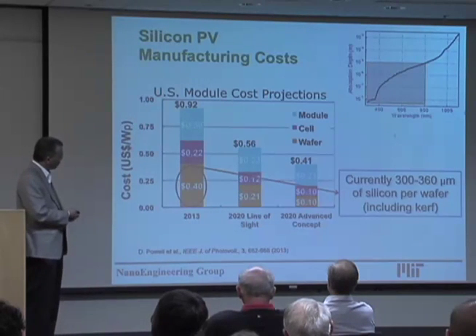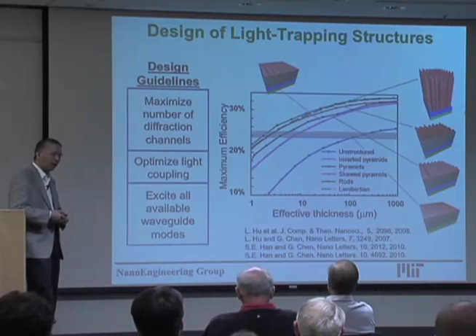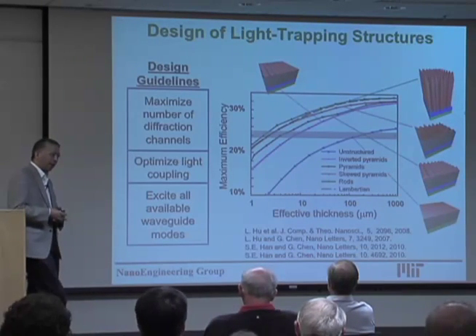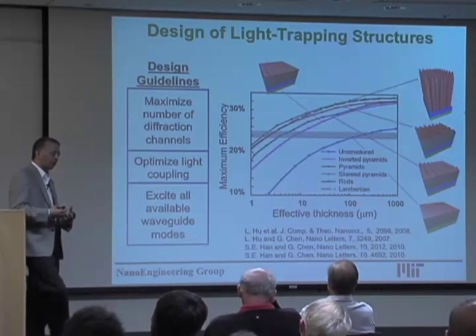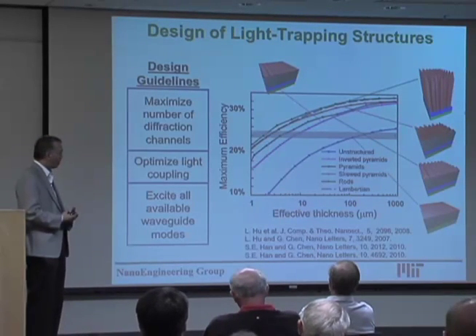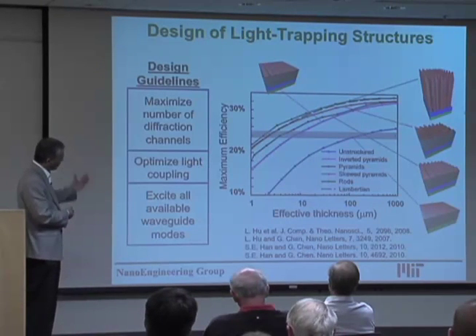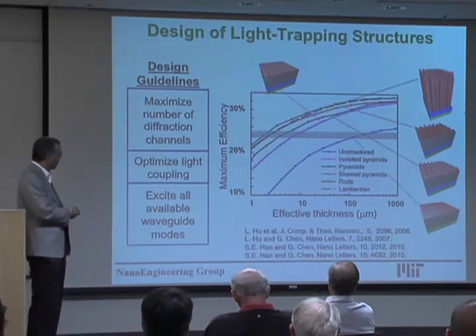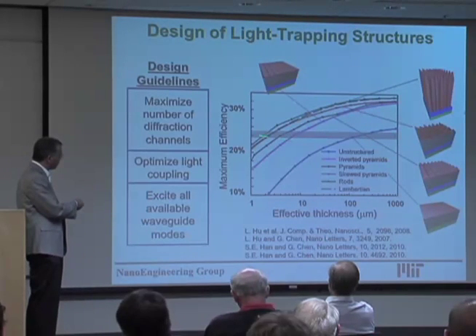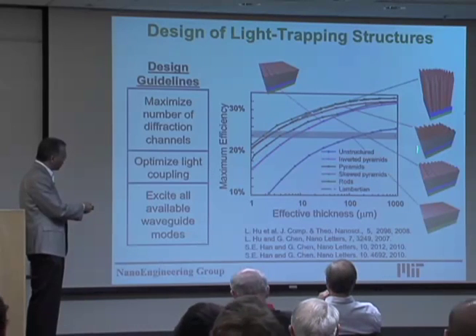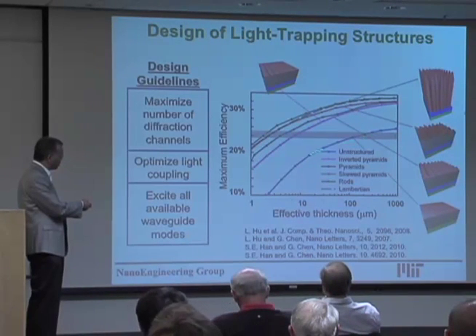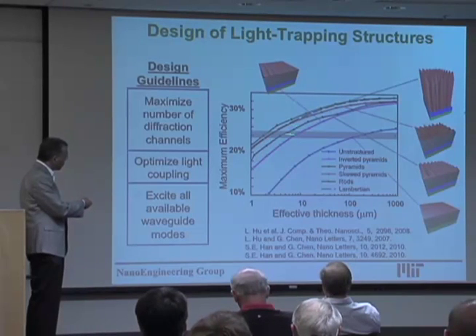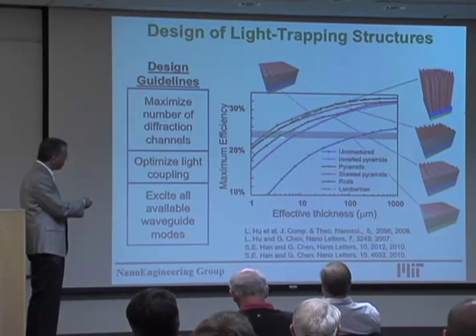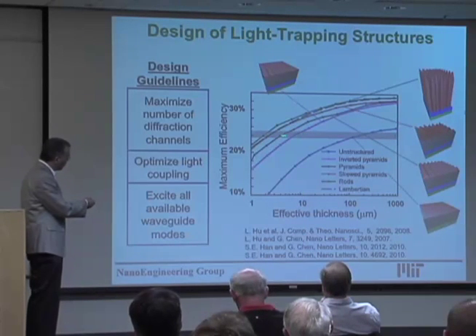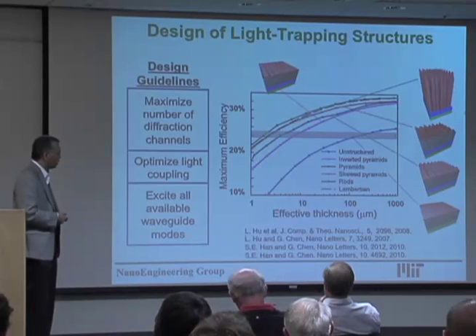Like I said, when we started looking into this, we looked into nanowires and plasmons. But at the end, after we considered the charge transfer and looked into different structures and how much surface area we increase, we ran these simulations. Basically, compared to a wafer with an anti-reflection coating, with a structured surface we can get within 10 microns a similar efficiency as thick wafer-based silicon cells.